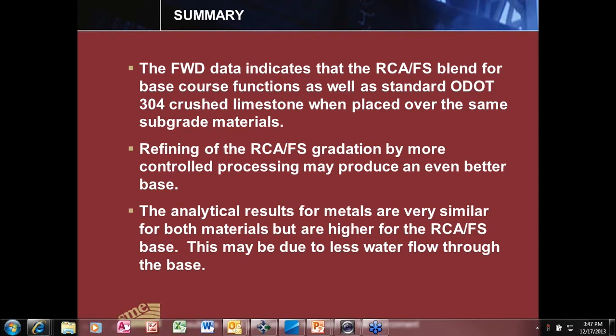Question is, what is the percent foundry sand used in the recycled concrete foundry sand mix? It's approximately 12% foundry sand, with the rest being recycled concrete. Again, with better crushing and blending methods, we believe that we can increase the percent foundry sand, possibly as much as doubling the amount with better processing of the concrete.